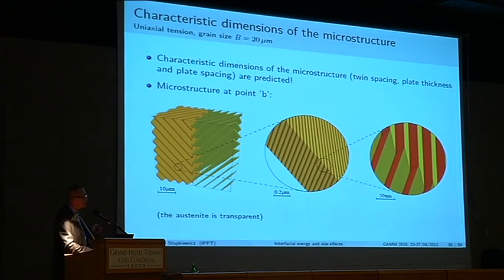So this is all predicted in an incremental manner, the evolution of these parameters. And this is done without introducing any artificial parameters. We only use essentially these three parameters that we need: the atomic scale energies and then our estimates for the elastic strain energy.